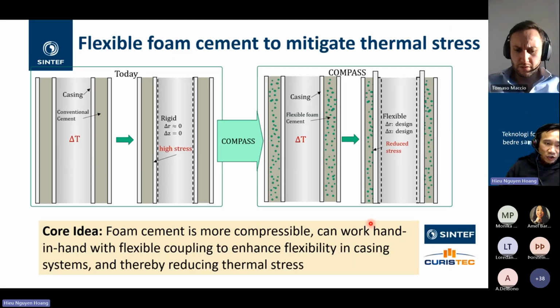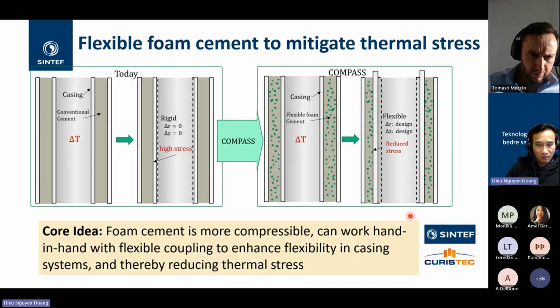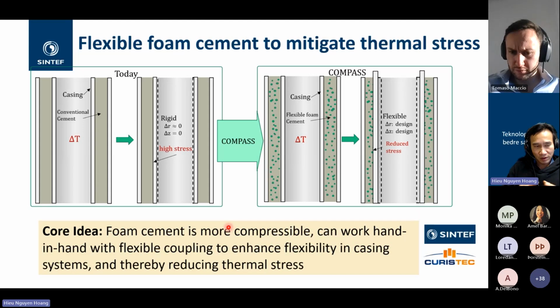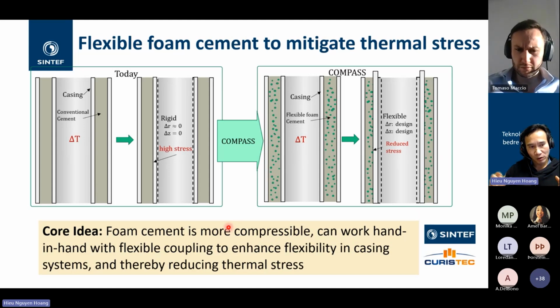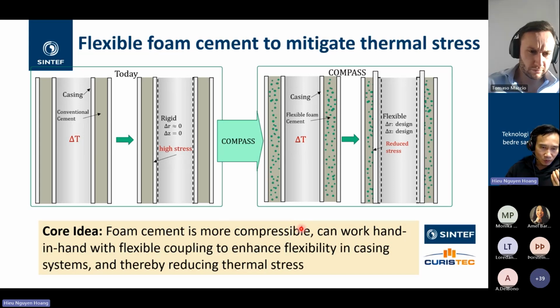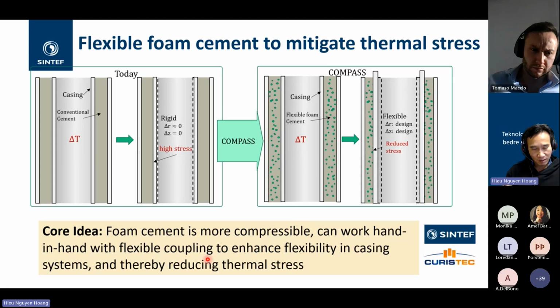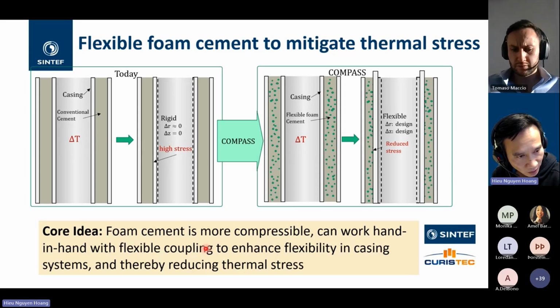And another key innovation that we're investigating in this project is a flexible foam cement. The core idea is that we would like to increase the flexibility of the casing system as a whole, not only in axial directions by flexible couplings, but also in radial directions. So the foam cement is, as you notice, more compressible, and we believe that it can work hand in hand with flexible couplings in order to enhance the flexibility of the casing system as a whole, and then we can reduce thermal stress. This is the principle behind this core concept.